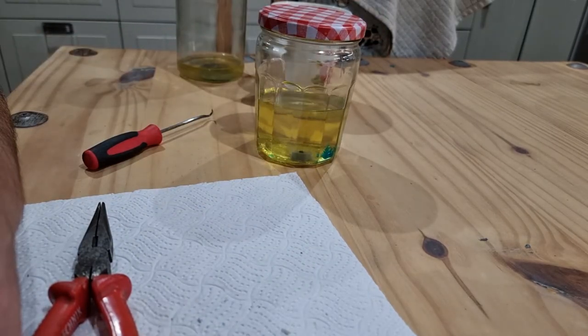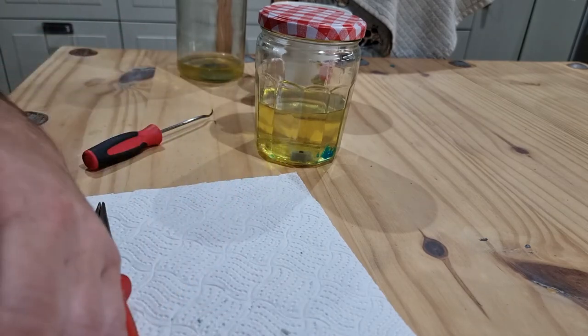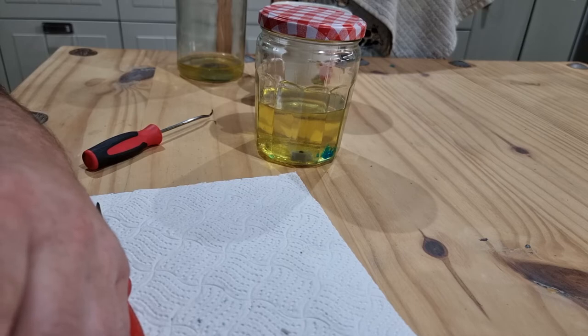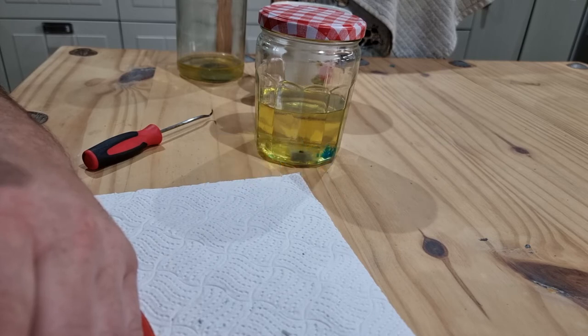I'm going to order some of that because we've pretty much got a design that works dimensions wise. It's just a case of making sure it works materials wise. I've just had some feedback from Andrew on the 700 to 1100 version. We tried the clear tuff and it didn't like the heat. I think it had a 60 or 70 degree, I'll check before I post the video up, 60 or 70 degree glass transition temperature. And in my mind I'd always said we want 80 degrees as a minimum.